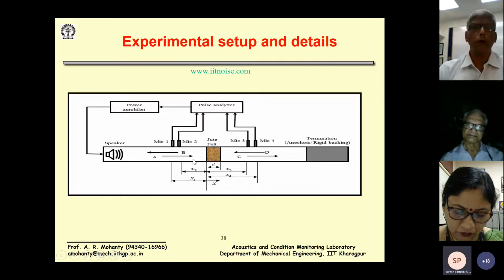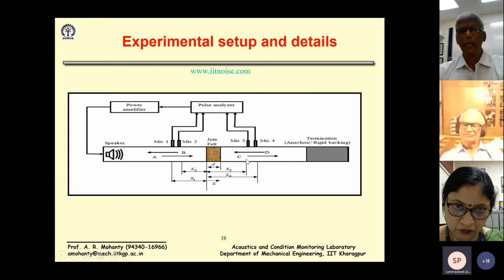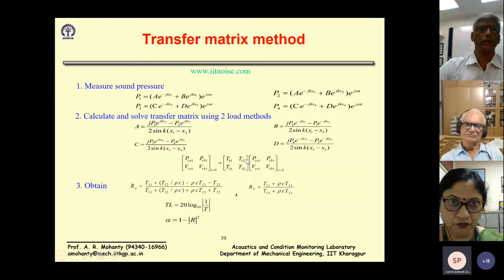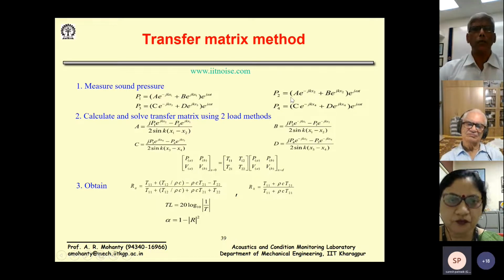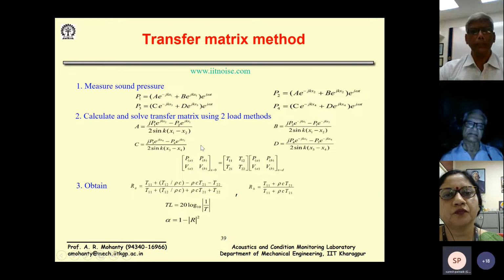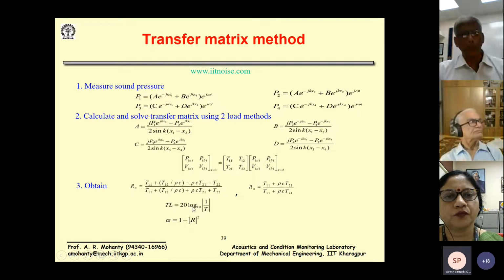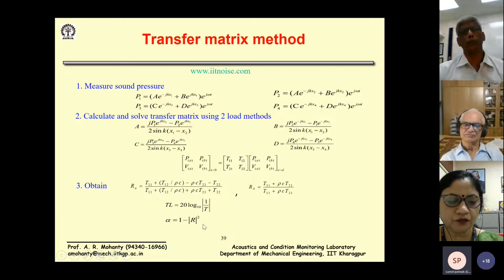Okay, what you have to know is X1, X2, X3, all these distances, and you have to do a simultaneous FFT analysis. So by knowing this pressure P1, P2, P3, P4, solving these equations, I can find out A, B, C, D, and plugging back A, B, C, D, which I have written here as T11, T12, T21, T22, I can find out the transmission loss, and I can find out the sound absorption coefficient.